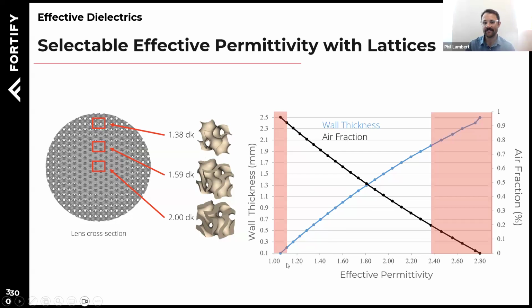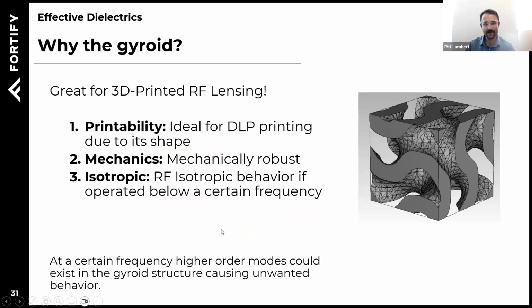We have manufacturing limits. Our manufacturing limits are how thin of a wall I can print, and that is represented here. I can't go down to air because I can't print an infinitesimally thin wall, and so I'm limited at some point. And then I can't print an incredibly teeny pore. I have to clean those pores out, and I have to have access to clean those pores out. And so we are limited in terms of effective permittivity ranges we can achieve by the geometry of this unit cell. But we do like it, and we like it for its printability.